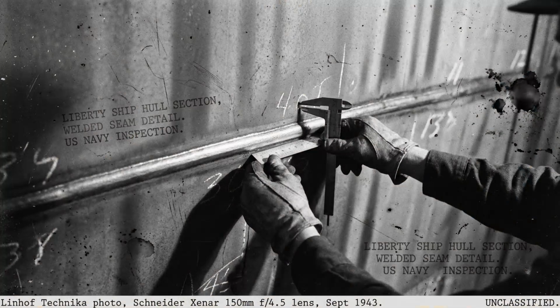Nearly 1,500 instances of significant brittle fracture were recorded during the war, and 12 ships actually broke completely in half, sometimes in calm seas without any enemy action at all. The problem was not the welds themselves, but the steel and the design of the hull. The breakthrough came from an unlikely source, a British metallurgist named Constance Tipper, working at Cambridge University.